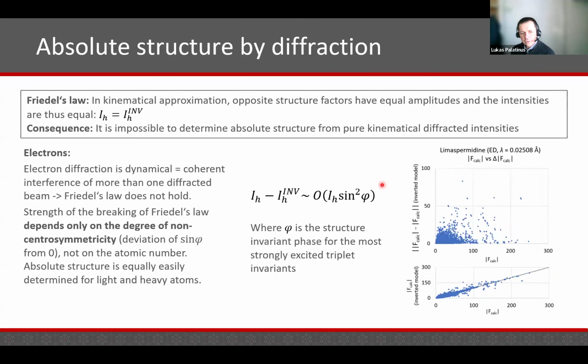On the other hand, for electrons, the effect that breaks Friedel's law is dynamical diffraction. And the amount of breaking does not depend on the atomic number. It's equally strong for light atoms and heavy atoms, and therefore it's possible to determine the absolute structure equally well from light and heavy atoms. And even better, the effect is large.